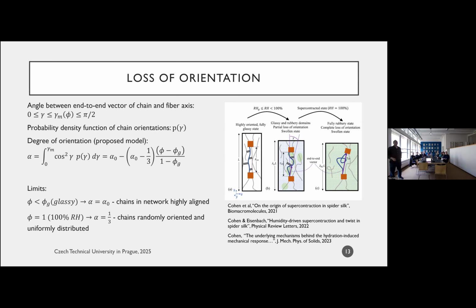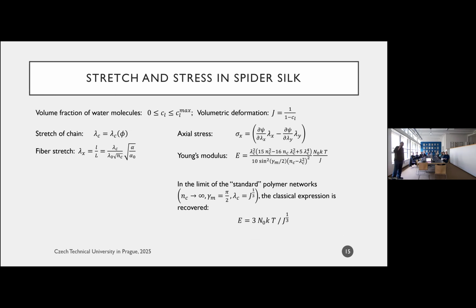So once we had this, we defined the volume fraction of water molecules. We were able to compute the volumetric deformation, the stress, the stretch of a chain, the fiber stretch. We're able to compute pretty much everything after we had this, right? And then all we had to do was run the calculations and see if this model fits the experimental results. I should also point out, if you take the appropriate limits here, you can also come up with an expression for the Young's modulus. So this is the expression that we got. It's long.